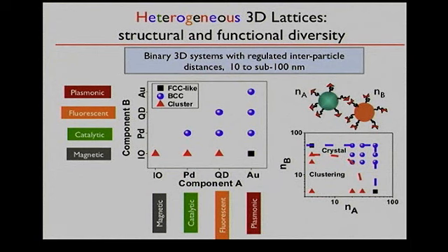More detailed information on those systems reveals that we can also understand to some degree where the system goes from clustering behavior to crystalline. For particles of similar sizes, one of the major parameters is the number of linkers, or DNA arms, which a particle has, and when it's around 20 or 30, clustering typically occurs. With more than that, we typically have a transition to crystalline organization of those materials.